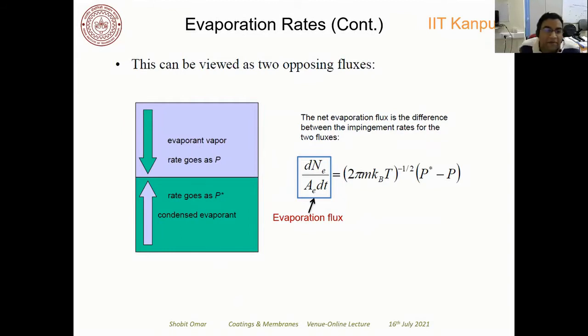Okay, this is what I'm talking about. You can see that this is the condensed phase and this is your vapor phase, and two types of fluxes are coming. One flux is coming from the condensed phase, the other one is coming from the vapor phase onto the condensed phase. So as I was saying, the evaporation flux is basically a function of P star minus P, and this is the constant which depends upon the temperature. Flux, as you see, is the number of atoms coming per unit area, per unit time. So this is how you define the flux. This Ne is the number of atoms which are evaporating from the condensed phase to the vapor phase.